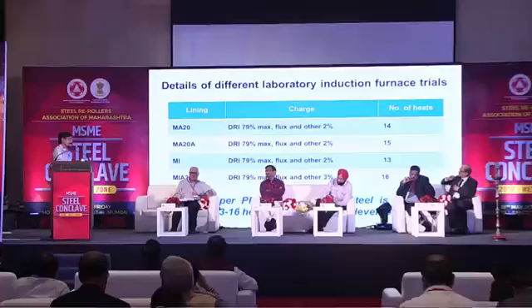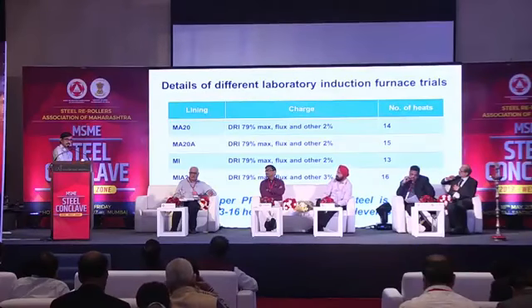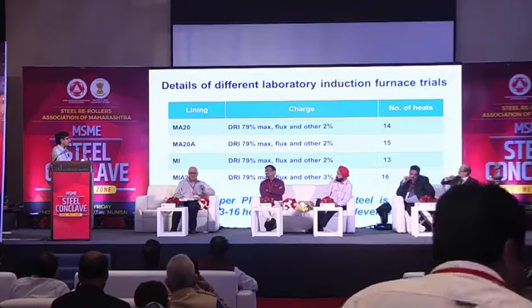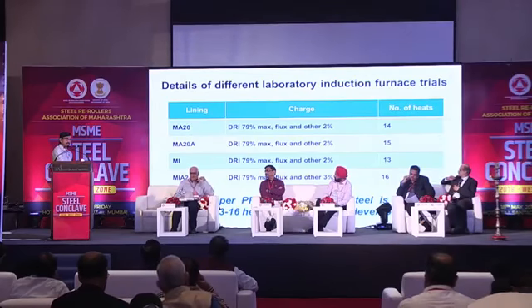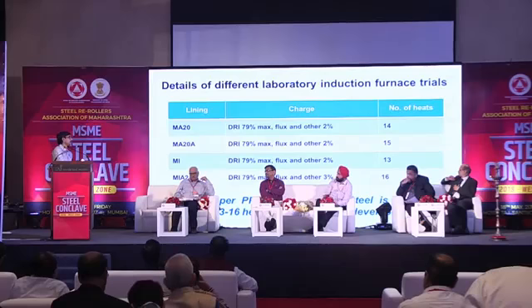So now we work with these. Now you see, in all of these the DRI content is 79 or 80%, and 20% is scrap, and on average we are getting 13 to 16 heats, and a maximum of 19 heats we have achieved.